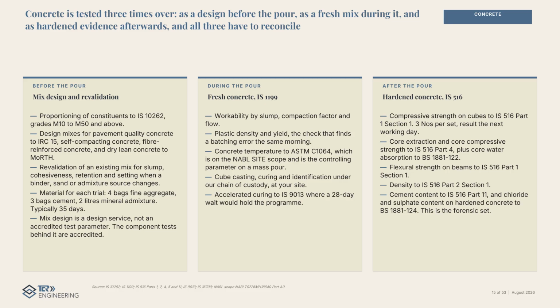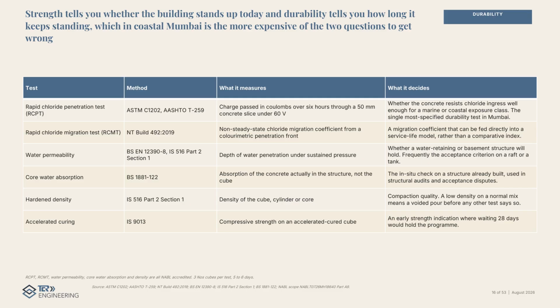During the pour, we measure workability, plastic density, and, critically, concrete temperature to ASTM C1064, which sits on our accredited site scope. After the pour, we measure compressive strength on cubes, on extracted cores, flexural strength on beams, density, and where there is a dispute, cement content, and chloride content on the hardened concrete itself. That last set is the forensic one. Strength tells you whether the building stands up today.